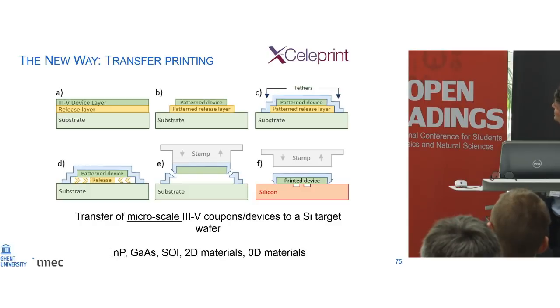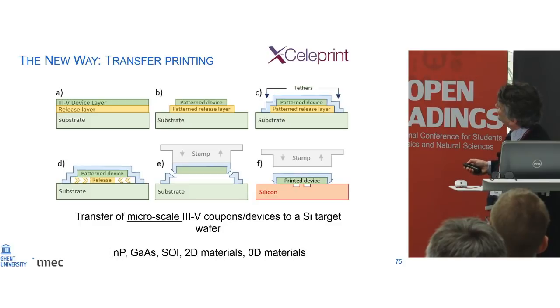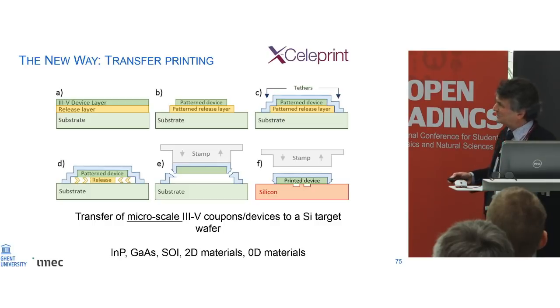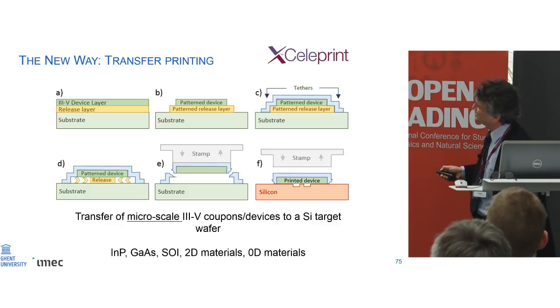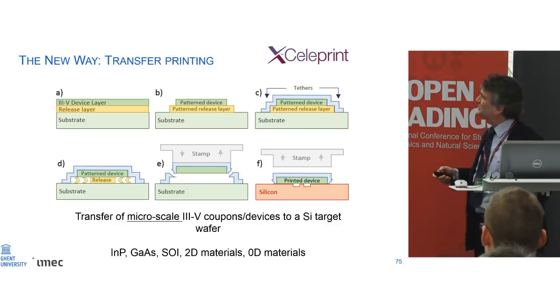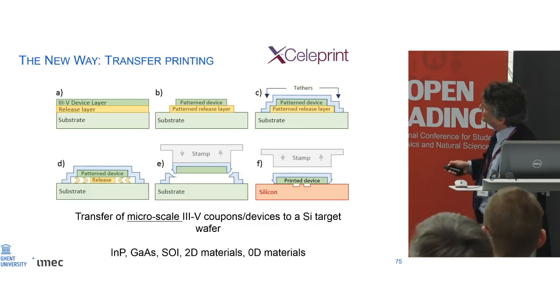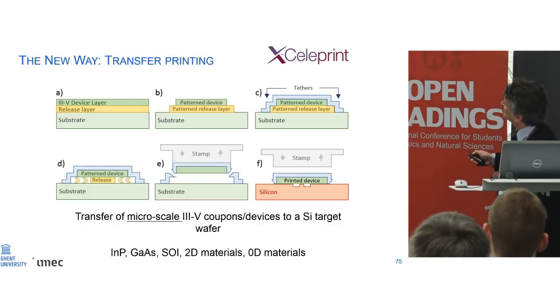I mentioned transfer printing, but I'll not dwell too much on this. But as I say, in transfer printing, what we do is we make sure that at some point the device, this is a DFB laser, for example, a III-V laser, is made ready to be picked up. But of course, to be able to pick it up, you have to make sure that the layer underneath is gone. So we selectively etch away the layer underneath the laser device, keep it in place by a few tethers here, and then with a stamp, the rubber stamp, pick it up and bring it to the silicon. That's essentially what we do.